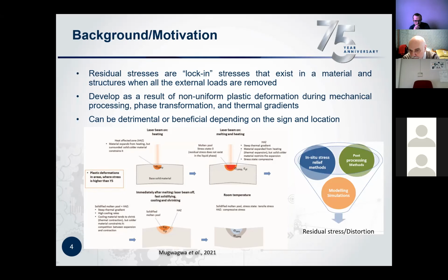There are methods currently being used to understand this phenomenon and find ways to manage it. There are in situ stress relieving methods, which rely on optimization of processing parameters or preheating of the base plate to minimize temperature gradients and residual stresses or distortion during the build. Some methods rely on post-processing, where you apply heat treatment to get rid of the stresses before you remove the part from the base plate. You do some stress relieving and annealing, then you know the stresses are alleviated, and you can remove your part. There are also modeling and simulation efforts where these things can be predicted well in advance before attempting to build a part, identifying areas of concern, adding supports, or applying control measures to manage those problematic areas.